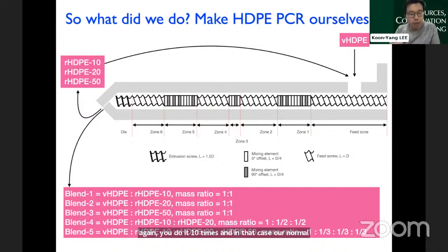And you also run some of the virgin polyethylene through the extruder 20 times. So that's -20. And lastly, the poor student Andre doing this work, run virgin polyethylene through our extruder 50 times. So that'll be rHDPE-50. So those are your virgin polyethylene recycled 10 times, 20 times, 50 times. All right. We then mix these 10, 20, 50 times recycled polyethylene with virgin polyethylene to then create these blends of multiple parts of high-density polyethylene that are recycled multiple times with virgin polyethylene, like what we described previously in our supply chain.